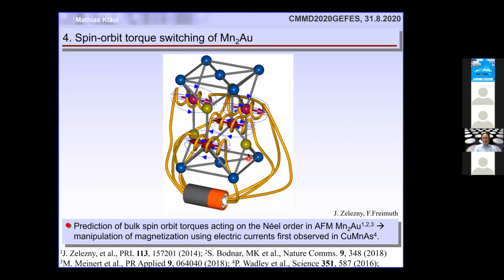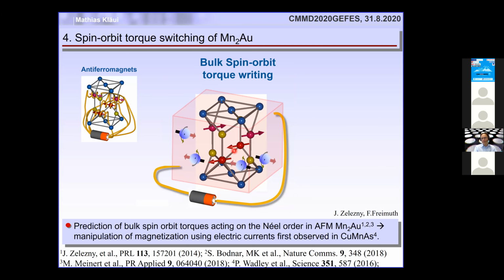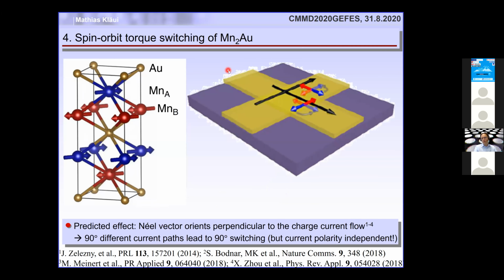So in a very nice picture by Frank Freimuth, you would like to have a torque exerted by a coil which is wound differently along the A side and the B side. So here you have kind of a counterclockwise winding of your coil, and here clockwise winding. And so then what you would like is that these two sublattices rotate in opposite directions, so that you actually get a 90-degree change of the total Néel vector. And this, as I said, was first observed in copper manganese arsenide, and then we looked at manganese two gold, and the prediction is that if you inject a current along two perpendicular directions, then the Néel vector will rotate by 90 degrees in a direction perpendicular to the current. So if I apply current this way, the Néel vector will rotate that way. If I apply a current that way, the Néel vector will rotate that way.